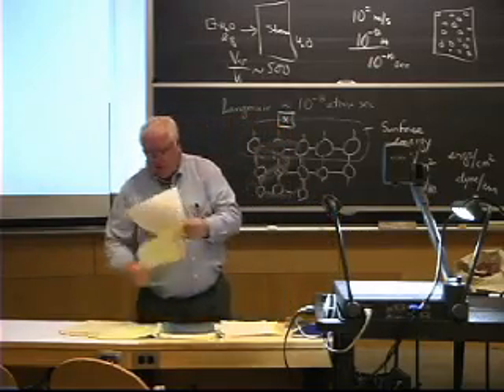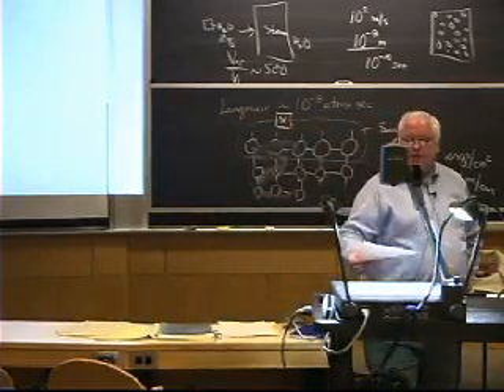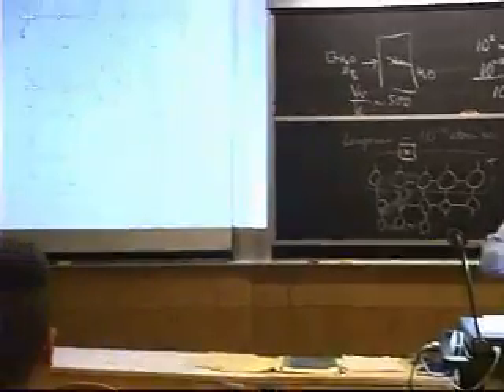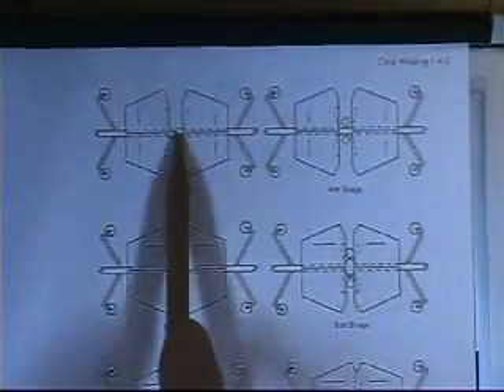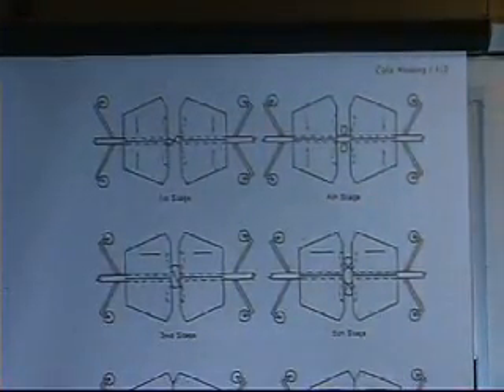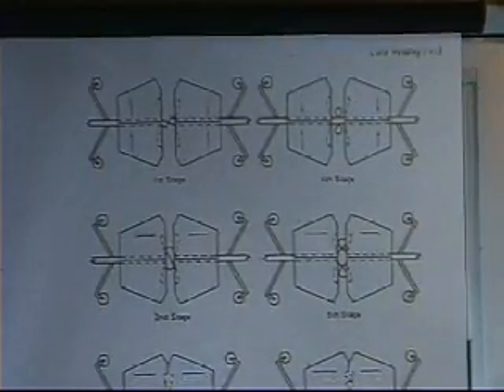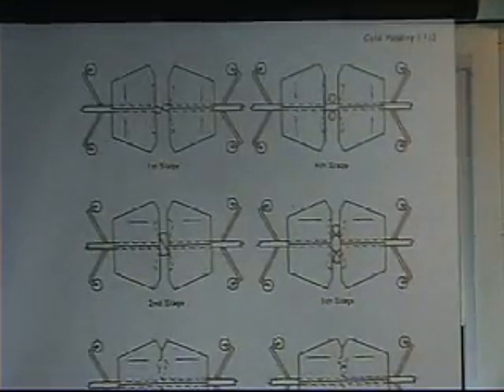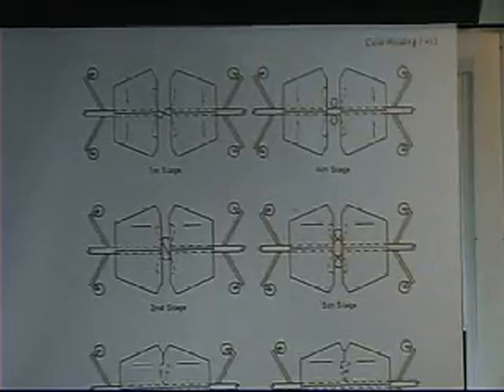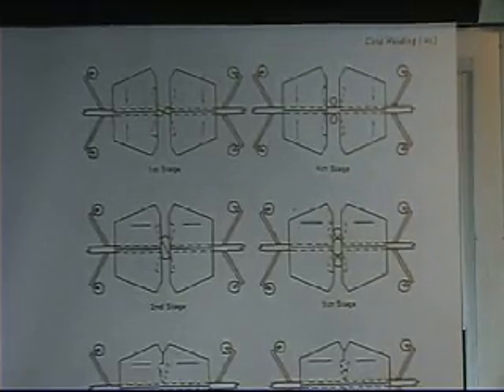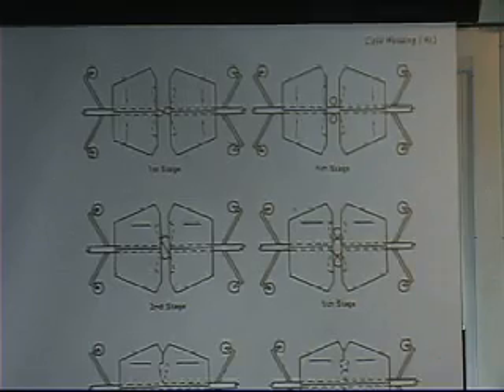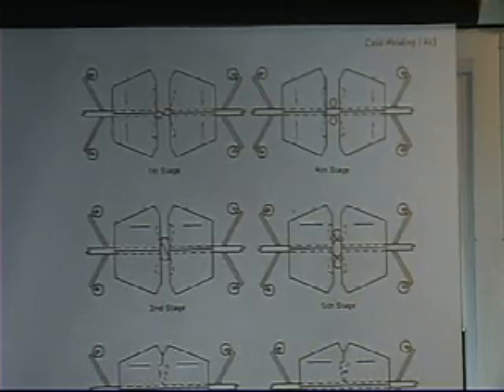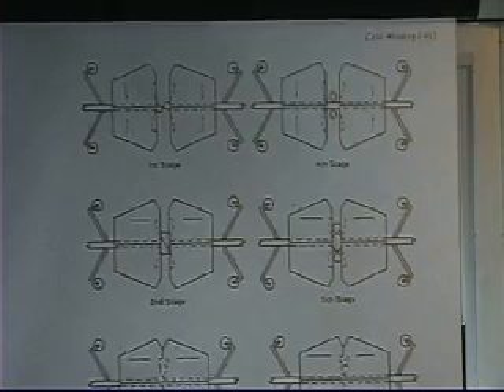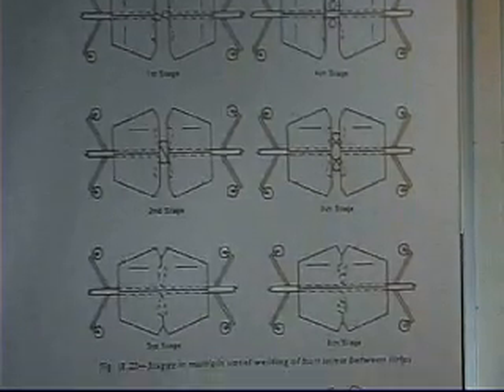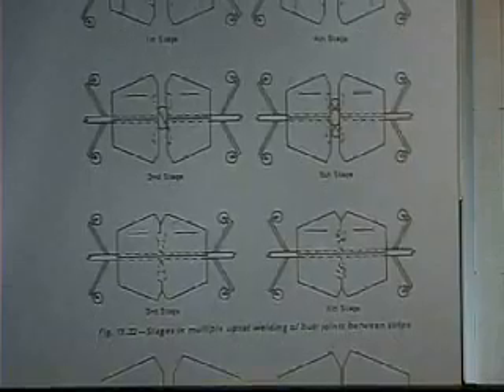One of the ways to do it is to just push them together and get a lot of shear. These are dies that are going to grab this aluminum wire right here, and they're going to kink the wire sideways a little bit and just smash it together and shove it together and just keep doing it to shear away the aluminum oxide, getting mechanical action shearing away the contaminant, getting enough deformation that I get 100% area of contact.